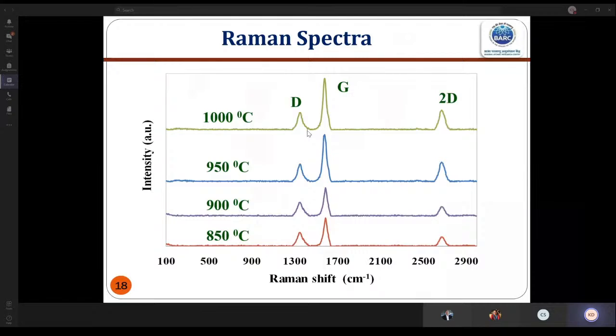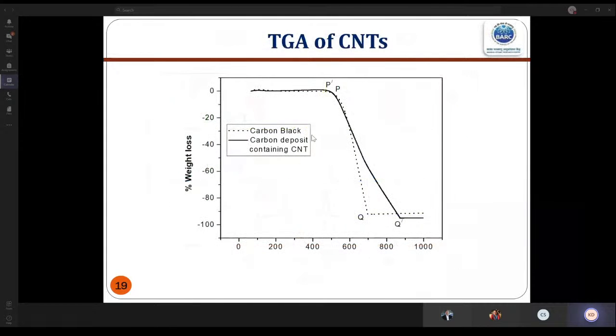As soon as we get the product, making the sample for electron microscopy takes some time. But we can use Raman spectroscopy, which is a typical characterization technique by which we can understand whether it is multi-wall or single wall. We can have characteristic D, G, and 2D peaks for multi-wall carbon nanotube, but for single wall it will be different, that I will show. We also do thermogravimetry to find out the purity. We oxidize some amount of material in the presence of oxygen or air, and from the weight loss we can calculate the amount of amorphous carbon or other impurity present in it.